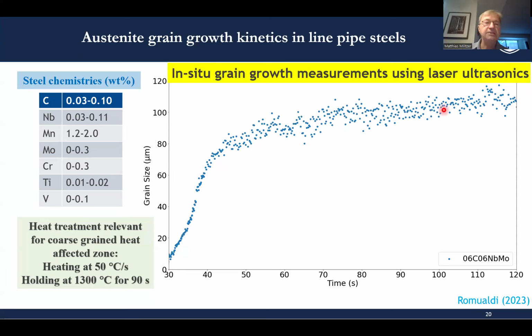So that's related to the presence of titanium nitrides that are strategically added to these line pipe steels to minimize austenite grain growth. And then some of the grain growth occurs during the heating stage. And at around 1100 degrees Celsius, we assume that niobium carbides would go in dissolution. So this leads also to an apparent increase in the grain growth rate, reduced pinning from the niobium carbides. And you see that with one test, you get hundreds of measurement points.